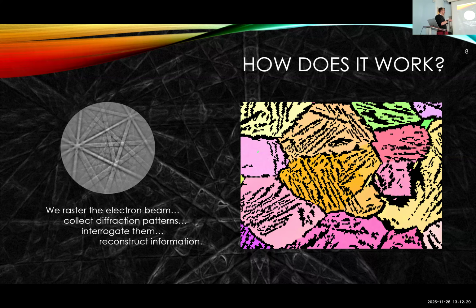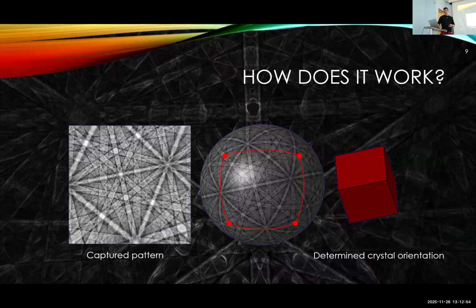And then once we've done that classification of orientation, phase, perhaps pattern quality, and a few other metrics, we can then reconstruct a map to describe that microstructure. And then we can look, for instance, at regions of common orientation and call that a grain. We can look at the interface between those and look at the character of that boundary. So we do this many, many millions of times in a typical experiment.